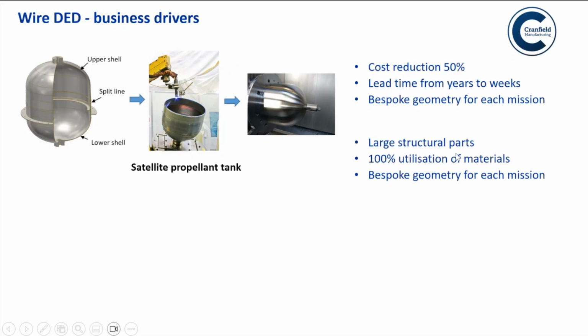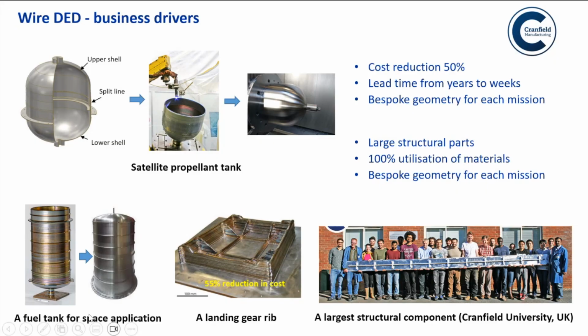Two more examples on large structures. The advantage is 100% utilization of the raw materials and bespoke geometry. From left to right, they have made a fuel tank for space applications by welding thin titanium wires layer by layer. BAE Systems, working with Cranfield, made a landing gear rib. They claim a 55% reduction in cost compared to machining from a forged block of material. Then they made the largest structural component as a demonstrator. It is several meters long and was held by the whole group of the Cranfield manufacturing center. In the middle is Professor Williams, who leads the center.